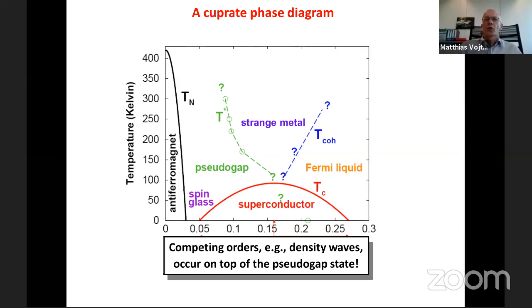The spin glass is a short-range ordered state. This has been characterized by neutron scattering to some extent, and NMR also in some detail. This phase diagram here may not be fully accurate for all cuprate families because some actually have a long-range ordered tail here at very low temperatures. In this regime, you also tend to see carrier localization, and you tend to see upturns in the resistivity which come from variable range hopping. This is presumably coming from a combination of Coulomb interactions and disorder. And whether or not the spin glass physics plays a crucial role in describing the conductivity is something which is not known, to my knowledge.